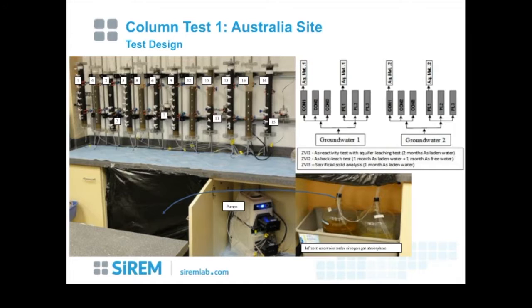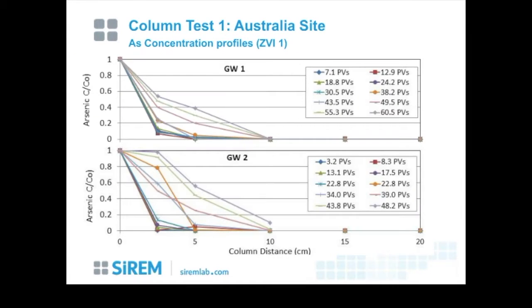The column 2 was zero valent iron run for a month with arsenic impacted water, and then flushed for an additional month with arsenic free water to determine if the arsenic would be back leached from the zero valent iron. And column 3 was essentially a replicate of column 2, but used as a sacrificial sampling device so that we could sacrifice that sample for spectroscopy and some of the leaching experiments that needed to be done.